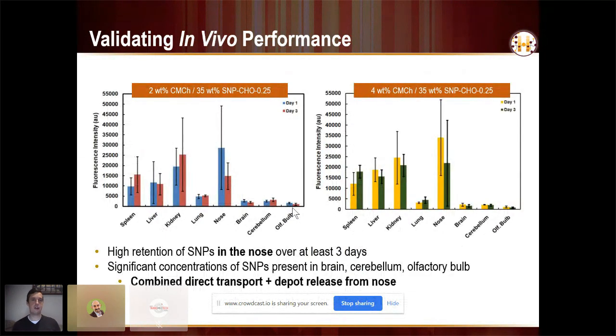And we've seen when we tracked the biodistribution of these materials that a lot of it gets stuck in the nose and stays stuck in the nose for the other 3 days that we looked at it. But a significant portion, not a ton, but a significant portion of the starch nanoparticles actually do transport into the brain. So we think that the benefits that we're seeing are a combination of some of the starch nanoparticles, as the gel degrades because of the reversibility of the Schiff base crosslinks, actively transporting through the nasal epithelium and to the brain through those pathways I showed you.